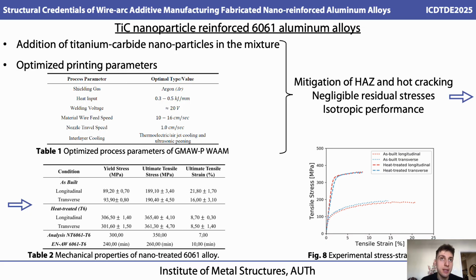Recent literature and experimental studies have shown that the addition of titanium carbide nanoparticles in the mixture of 6061 aluminum alloys can significantly reduce these disadvantages. We propose to optimize the printing parameters as well. Specifically, we propose the following optimized printing parameters of table 1. The shielding gas should be argon. The heat input should be limited to somewhere around 0.3 to 0.5 kilojoules per millimeter.